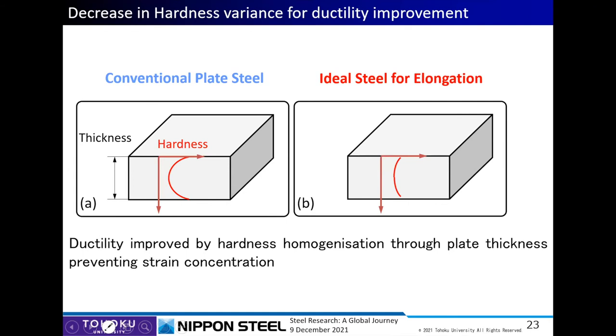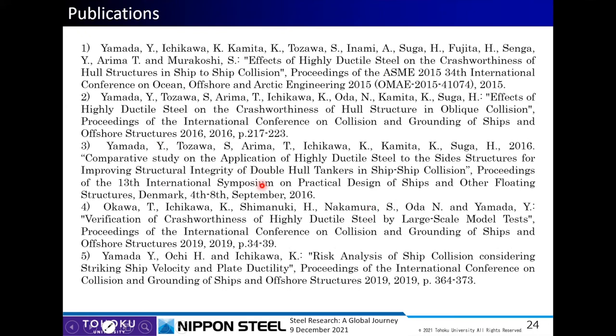Another key issue is that we reduce the variance of hardness throughout the thickness. Conventional steel plate has some distribution of the hardness, something like this. But our ideal steel for elongation has a minimum distribution of the hardness so that we can avoid stress concentration and get a better elongation. We made some publications shown here, so if some of you are interested in these issues, please find these publications later.